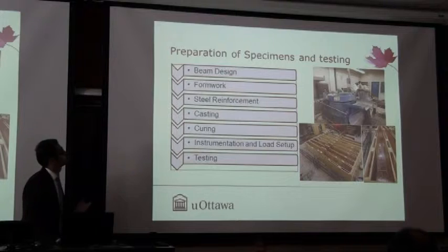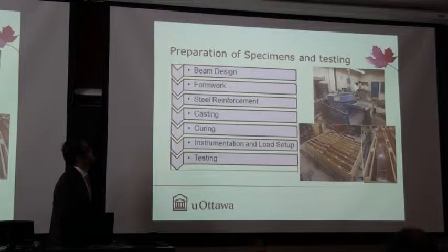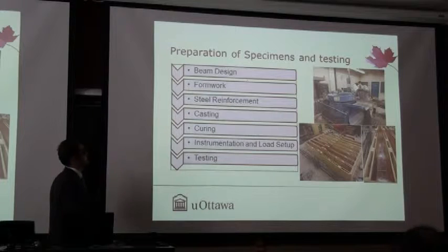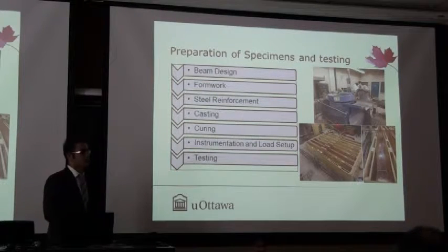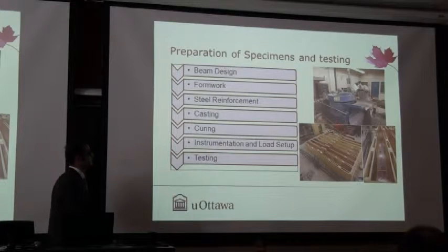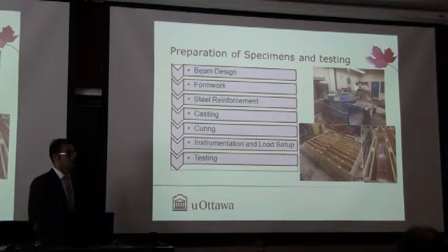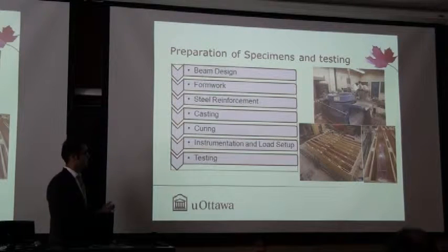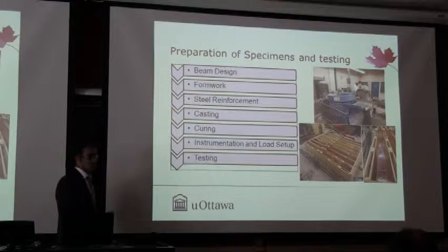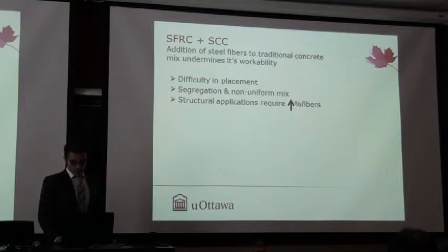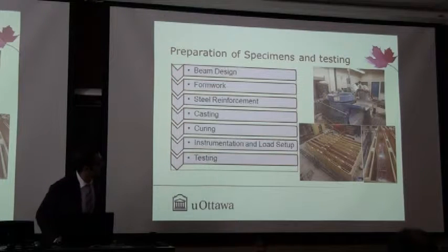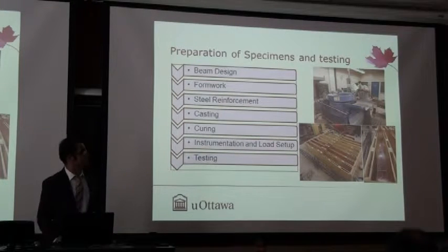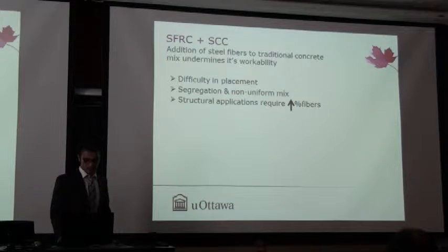As in most experimental research programs, we had to prepare the beams as the testing specimens. So we started with the beam design. We built the formwork and the reinforcement cages. We did the casting in the structural lab at the University of Ottawa. Then we did the instrumentation for measurement, and the loading setup, and then we started testing. You can see my formworks and cages in the bottom there, and the mixer that I used for preparing the beams.